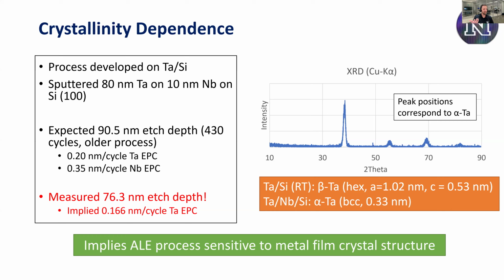We under-etched, and we think we under-etched because of the difference in crystallinity. We went back and confirmed that, and it was reproducible. So absolutely. I didn't actually think it would matter that much, but it did. So we had to redo all our samples. Or rather, they did. Brian did. I don't do anything.